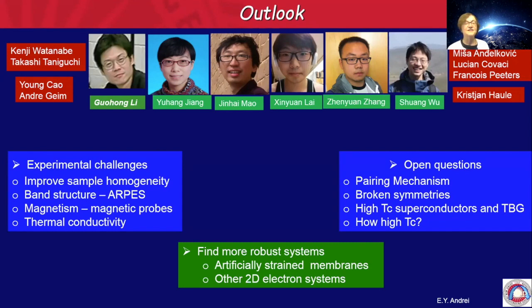So of course, we just scratched the surface of this field. It's a huge field with lots of interesting possibilities, but also with lots and lots of challenges. So we have experimental challenges. These twisted bilayers are extremely inhomogeneous. They're strained. There are defects included, and the sample homogeneity is a big problem. And maybe with more homogeneous samples, it might be possible to increase the superconducting temperature. Right now, the record is about 3.5 degrees Kelvin above absolute zero. So we have a long way to go.